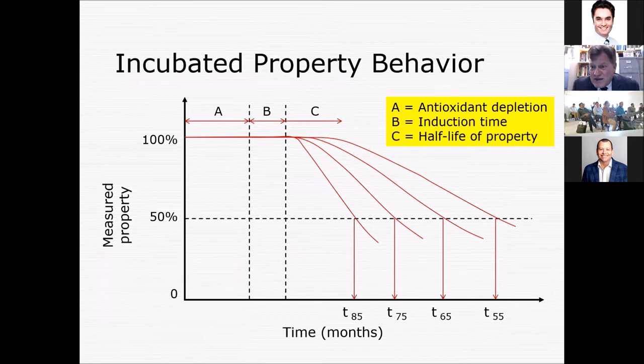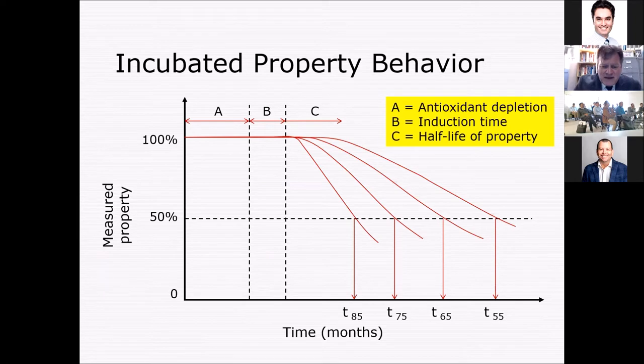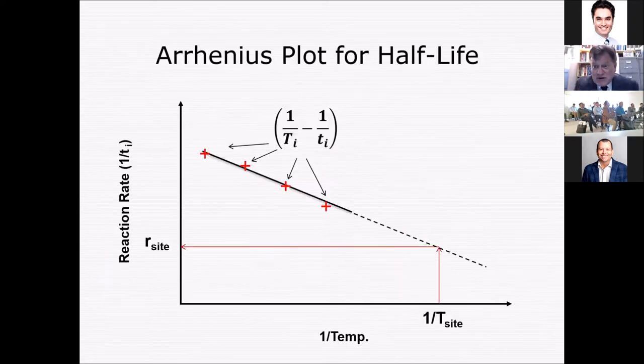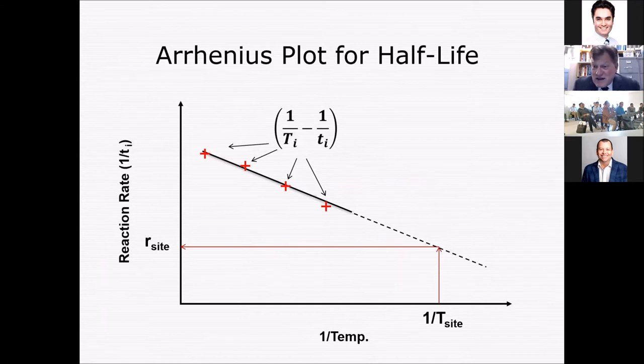You will run the experiment at a minimum in triplicate. Here we ran it in quadruplicate at 55, 65, 75, and 85°C. You beam over to that 50% value of the measured property, then plot it on an Arrhenius plot. The slope of that curve is important. Then beaming that down to the site-specific temperature is also critically important. Please realize this is the half-life — there is still life in the material, but this is conservative and you can hang your hat on it.